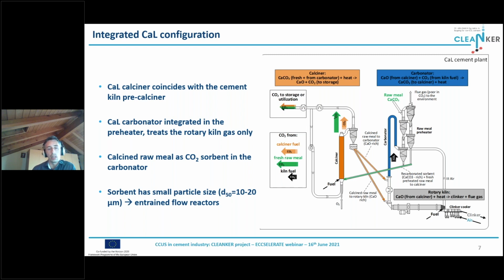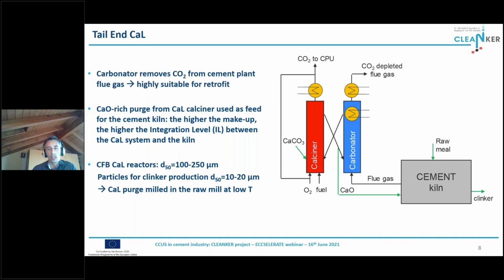So we automatically get rid of the two main CO2 streams of our reference case. The residual stream is coming from the rotary kiln and is captured by the carbonator, which plays the only role of capturing this residual amount of CO2. The main peculiarity of this system is that the sorbent used for capturing CO2 is the same material used for producing clinker. Since this material has a very small particle size, from 10 to 20 micrometers, we have to use entrained flow reactors, which is a different technology from the conventional fluidized bed system considered for the calcium looping process.